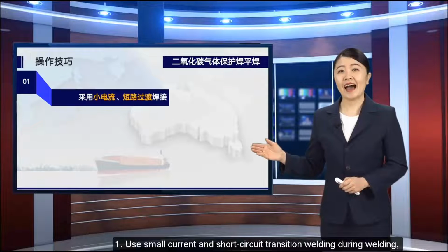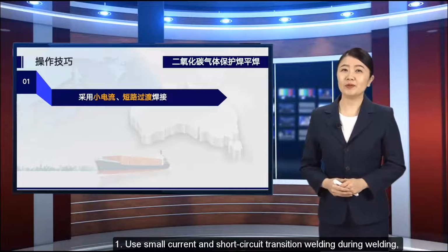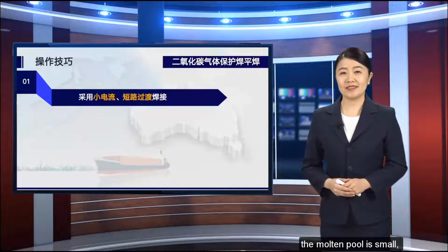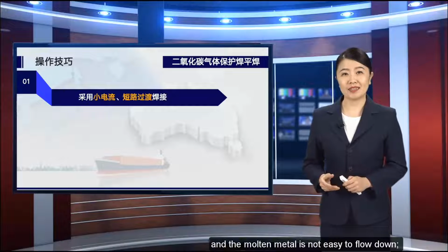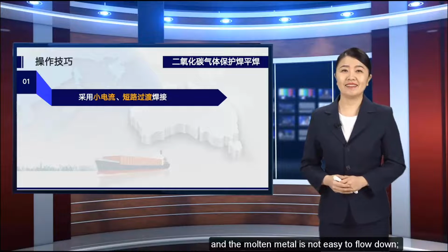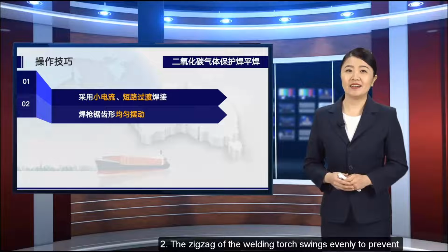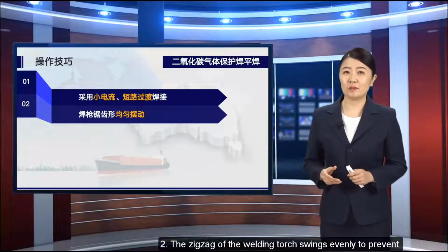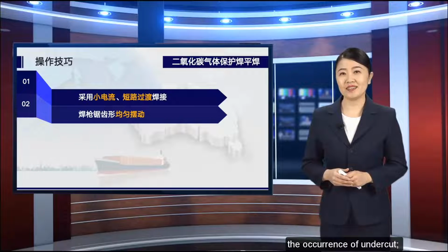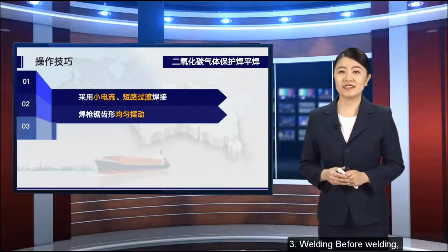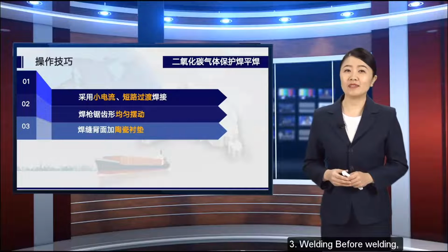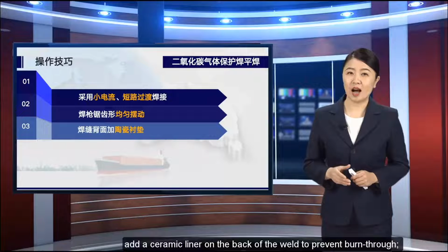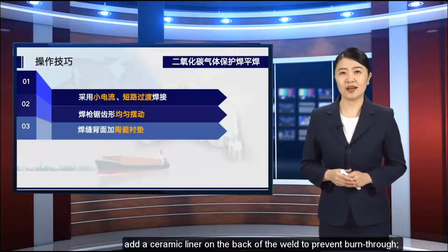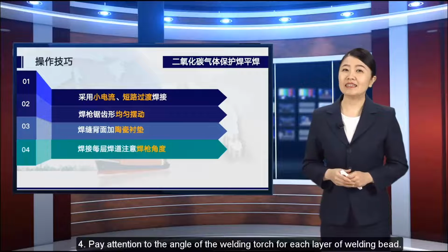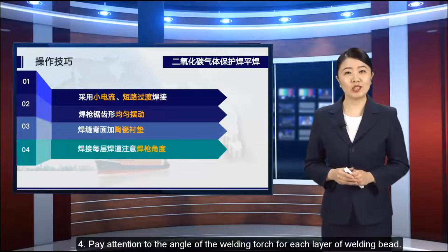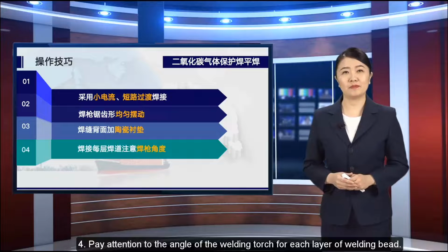1. Use small current and short-circuit transition welding during welding. The molten pool is small, and the molten metal is not easy to flow down. 2. The zigzag of the welding torch swings evenly to prevent the occurrence of undercut. 3. Before welding, add a ceramic liner on the back of the weld to prevent burn-through. 4. Pay attention to the angle of the welding torch for each layer of welding bead.